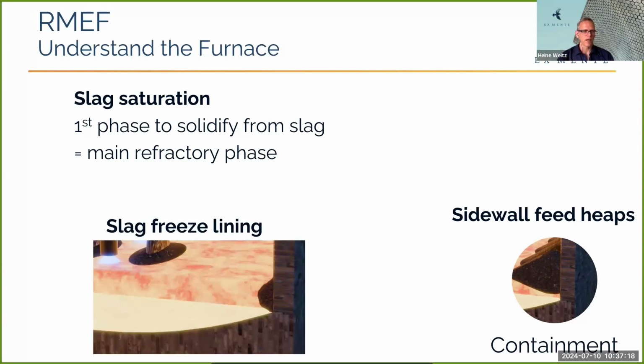Okay, then the last one is to have a slag freeze lining. So by carefully controlling your mass and energy balance, you may be able to form and to sustain a freeze lining that forms a barrier between your refractory material and your slag. So that negates the need to have a compatible slag and refractory material to a large extent.